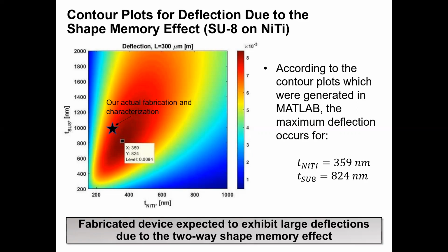So this modeled result helped to influence the MEMS bilayer design based on this approach. The fabricated device parameters for NiTi and SU8 thicknesses that were actually built in the next section are marked with a star on this graph. And based on this contour map, the device would be expected to exhibit significant amounts of deflection due to the phase change.